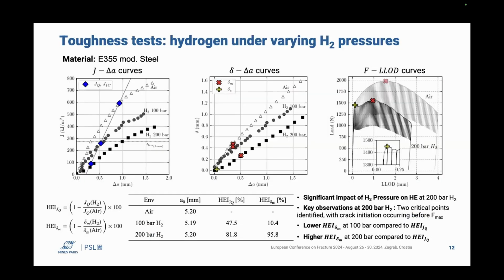Now some toughness results for the modern material. The white one is in air. We can see that the J0.2 millimeters is above the limit of validity, so it's not a valid result if you analyze according to the standard. But when we expose this material to 100 bar of hydrogen, the J0.2 is already in the valid zone. That is something interesting. And when we increase the pressure to 200 bar, it is still lower.